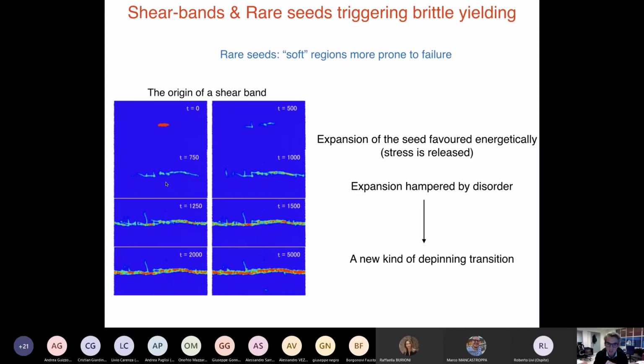And the physics of this relaxation through shear band is very similar to the expansion of a seed in the random field Ising model, in the sense that you have to think of a system which is extremely well annealed, so very low disorder, and then you start to deform. Since the system is very big, somewhere with a very small probability you have some region which is not so well annealed and which is more prone to failure than all the rest. And this region, which is more prone to failure, is where the failure will start. So if I fail here, I'm gaining energy because I'm releasing stress. But then once I fail here, if I want to propagate this failure, there is something that is blocking. And the thing which is blocking is that, in principle, the material is disordered.